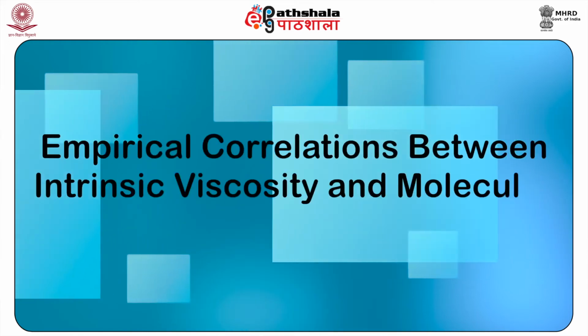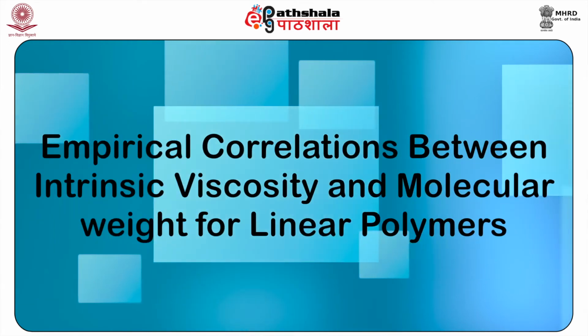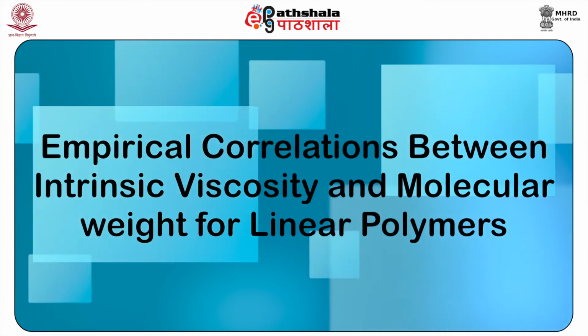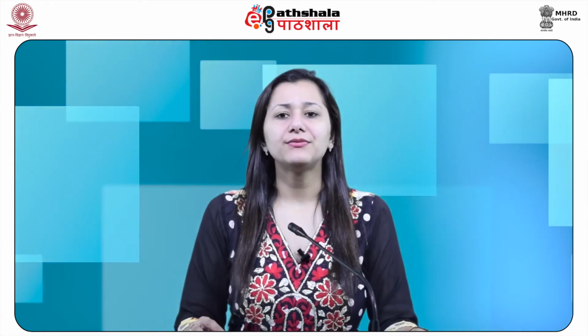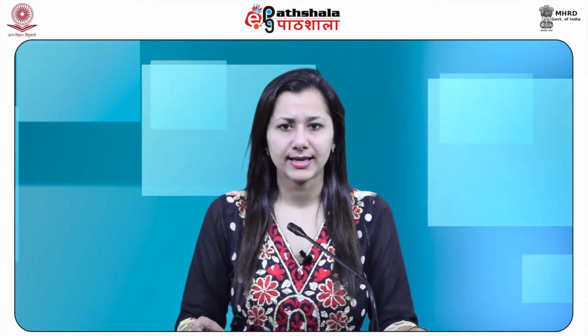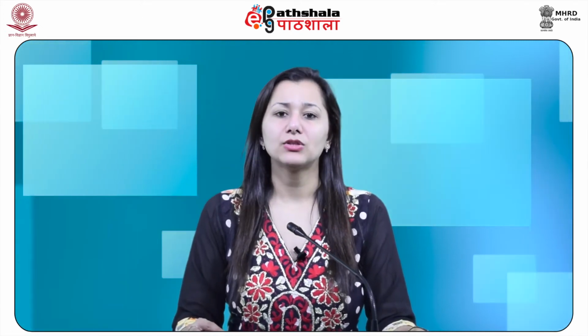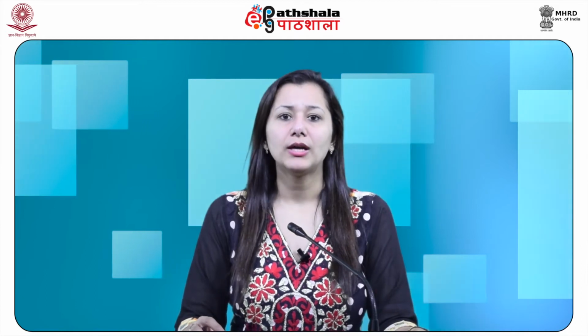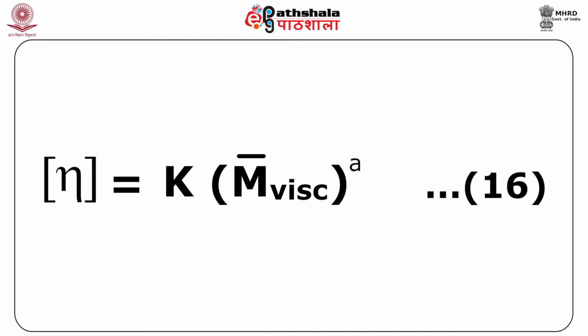Now we shall see the empirical correlations between the intrinsic viscosity and molecular weight for linear polymers. Staudinger in 1950 established that for a series of samples of the same polymer in a given solvent and at a constant temperature, the intrinsic viscosity, or the viscosity number, is related to the molar mass of the polymer by the equation known as the Mark-Houwink-Sakurada equation, formerly called the Staudinger equation. The intrinsic viscosity is equal to K times M viscous bar raised to the power A, given by